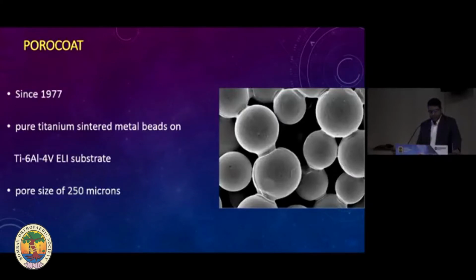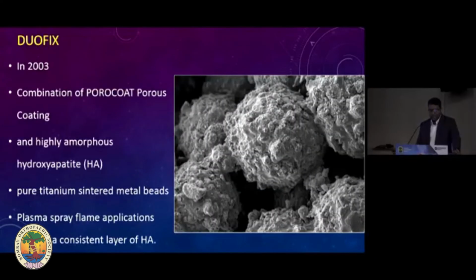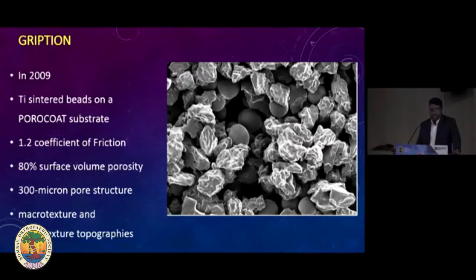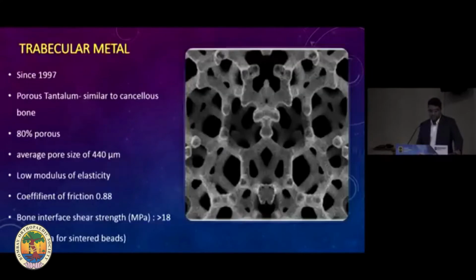Porocoat was one of the first, in 1977, when pure titanium was sintered onto the titanium alloy with a pore size of 250 microns. Then came Duofix in 2003, wherein Porocoat was coated with a hydroxyapatite layer. Gription came into being in 2009, where titanium sintered beads had an increased porosity, with 80% of the surface volume being porous, and an increased coefficient of friction. Trabecular metal, though appearing to be new, has been in the market since 1997, where we use porous tantalum, which is similar to cancellous bone with 80% porosity.